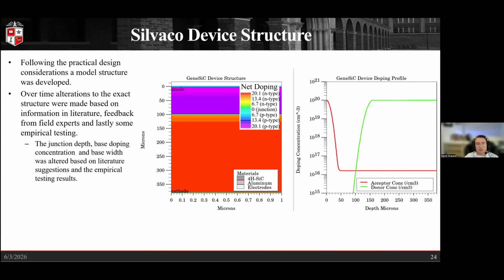And so based on that, we began to model the device in Silvaco Victory Device. So that's our TCAD software of choice. And then over time, we ended up making some alterations to the structure based on some literature, also some feedback from field experts over the duration of the research, and on empirical testing, right? The main goal was to characterize that physical sample and make the TCAD model match it. And so the final structure that we came up with was shown here. This does deviate slightly from the suggested DSRD structure. However, as I mentioned, based on some of that literature and feedback from field experts, we believe this device, while denoted as a DSRD,